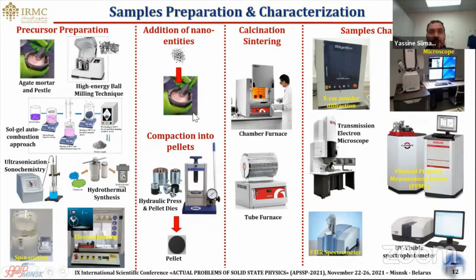Briefly, for the synthesis of high temperature superconductor materials such as YBCO or BISCO added with nanostructured materials, we adopted firstly to prepare the precursor. The precursor is a compound that does not contain any residue of carbon at the end. To prepare the precursor, different methods can be used in our laboratory, such as solid state reaction by hand grinding or by means of high energy ball milling.